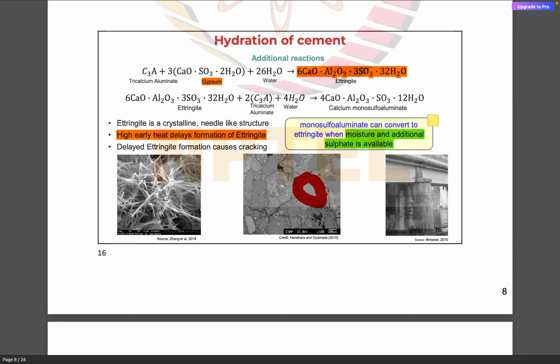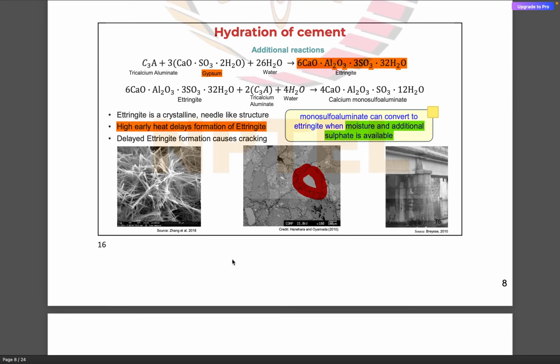So that leads to expansion of concrete, and the expansion of concrete leads to the cracking within the structure of concrete, and this cracking again allows the water to seep into the concrete, and that leads to corrosion of steel, and then subsequently the strength and stiffness degradation of the structures.